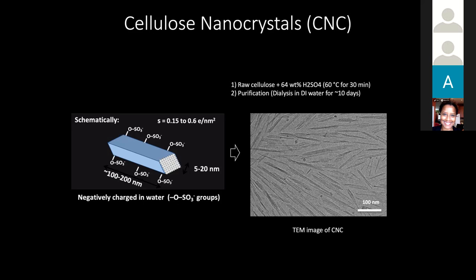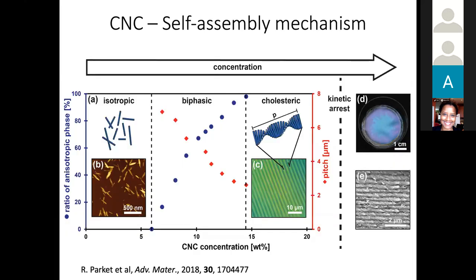So I don't know if you have done a little bit of colloidal course, but when you have nanoparticles of the order of a few hundreds of nanometers that are electrically charged, so you have a negative charge surrounding them, they can really maintain in suspension and be suspended. And what is nice is that in this system, they are colloidal particles, but they are liquid crystalline as well. So if you have heard of molecular liquid crystal, we have the cellulose nanocrystal, that we call CNC, are essentially a colloidal analog.